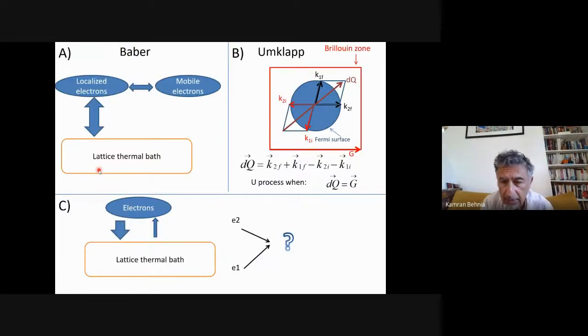So here is the puzzle. Neither the Baber mechanism nor the Umklapp mechanism can explain the persistence of T-square resistivity in this context. Somehow, when electrons collide with each other, the thermal bath takes a kind of tax on momentum exchange. You cannot avoid losing some momentum to the thermal bath when you are exchanging momentum with other electrons.